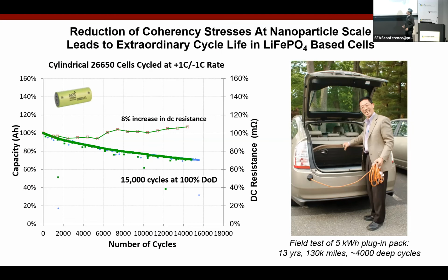And one thing we discovered was that this nanoscale lithium iron phosphate had exceptionally good life. And what was it about nanoscaling? Some of it was fairly straightforward kinetics. With smaller particles, you can transport ions in and out faster. But there also was an aspect of the fact that the storage of lithium in that compound involved the first order phase transition. It was a discontinuous phase transition.